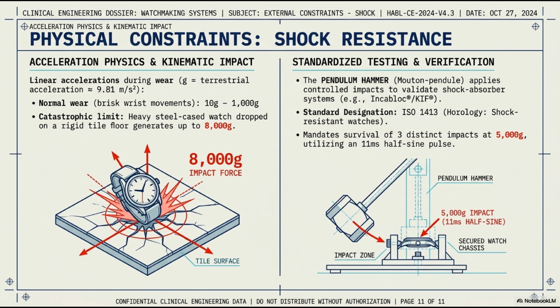How do we test against this? Look at the right side of the screen. We use standardized testing equipment called the pendulum hammer, or mouton pendule. This machine delivers highly controlled, scientifically repeatable impacts directly to the watch chassis to test the efficiency of internal shock absorbers like the Incabloc or KIF systems. To earn the designation of a shock-resistant watch under ISO 1413, the watch must survive 3 distinct, brutal impacts at 5000 g, utilizing an 11 millisecond half-sine pulse. If the watch stops, or if its timekeeping rate deviates beyond a few seconds, it fails.